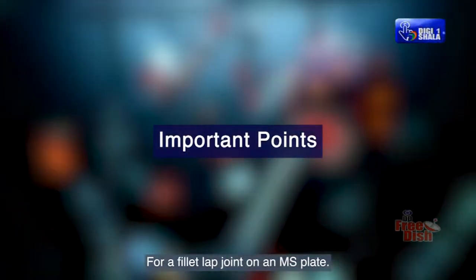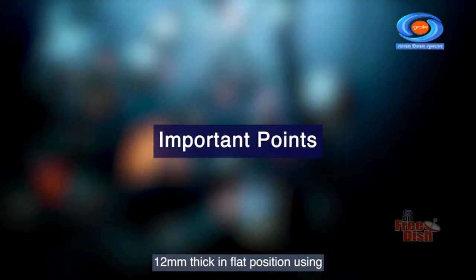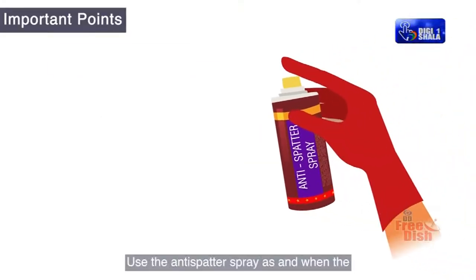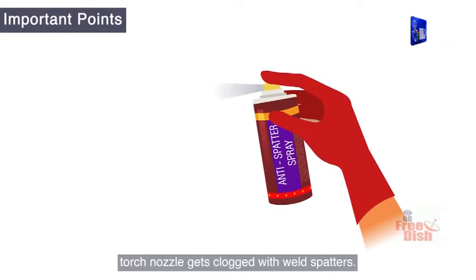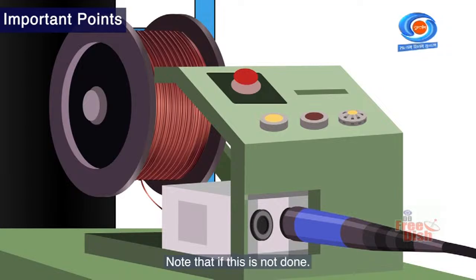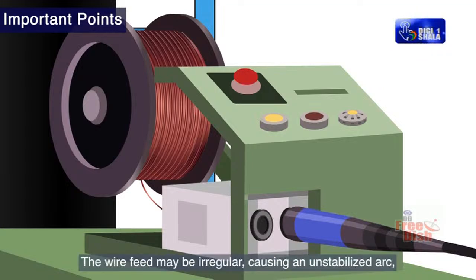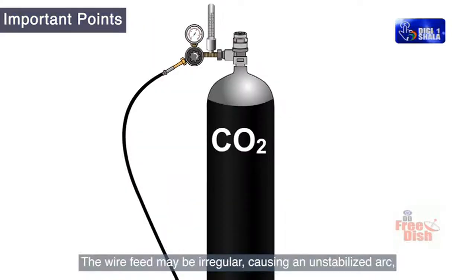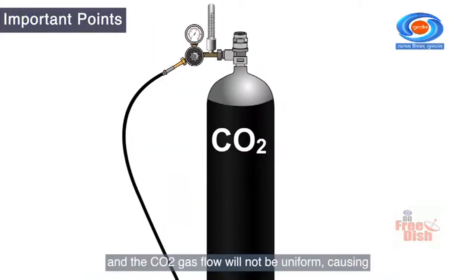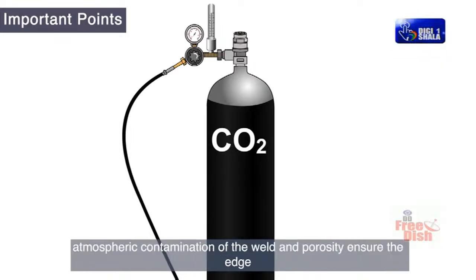There are some important points to be followed for a fillet lap joint on an MS plate 12 mm thick in flat position using gas metal arc welding process. Use the anti-spatter spray as and when the torch nozzle gets clogged with weld spatters. Note that if this is not done, the wire feed may be irregular, causing an unstabilized arc, and the CO2 gas flow will not be uniform, causing atmospheric contamination of the weld and porosity.